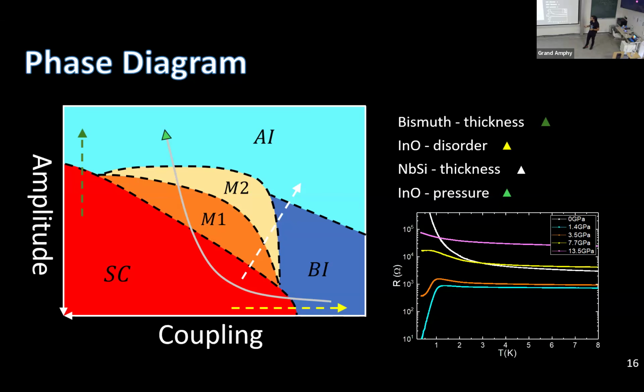So we believe that to be able to see these anomalous metallic states in your materials, you need a sample that has low superconducting amplitude in the superconducting wave function, but also a good coupling between the different regions in your system.